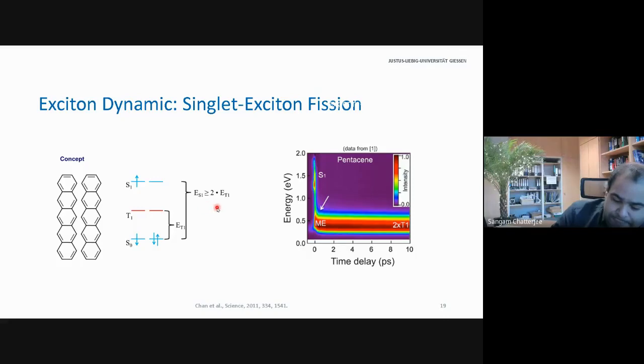You can think that if I have this scenario, I can excite one singlet state, and if the energy level configuration allows, this one singlet can split into two triplets, and thereby I effectively double the number of excited electrons by putting in only one photon. That should lead to carrier multiplication and to energy harvesting beyond the Shockley-Queisser limit for solar cells, which basically says that if I have one photon, I can get out one electron and the rest goes into heat. It cannot be harvested.